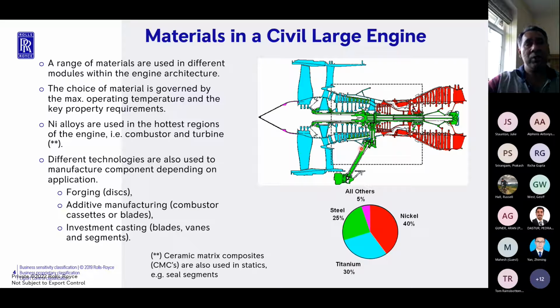So very broadly, what you would see is that it's primarily metallic. It's almost 95% metallic. And at the same time, you have a sizable amount of this, which is primarily nickel. And this nickel effectively forms the high temperature materials group, which myself and a few others form a part of.